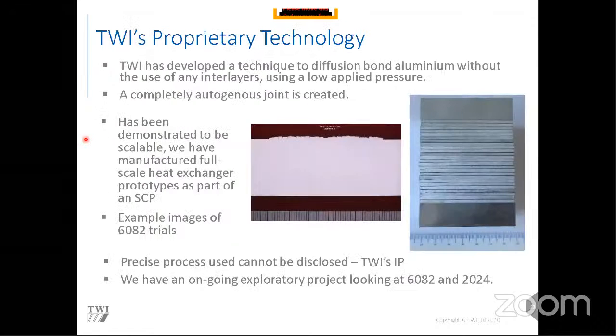So this is where TWI has developed some proprietary technology. We've actually developed a diffusion bonding technique where we can bond aluminium without the use of any interlayers, and using a low applied pressure we're actually creating a completely autogenous joint.